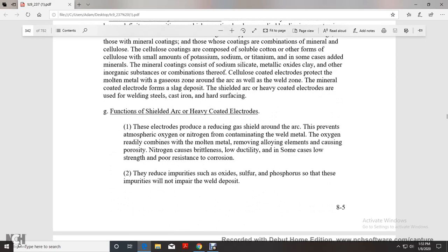Function of shielded arc and heavy-coated electrodes. One: the electrodes produce a reducing gas shield around the arc to prevent atmospheric oxygen or nitrogen from contaminating the weld. Oxygen combines with the molten metal, removing the alloying elements and causing porosity. Nitrogen causes brittleness, low ductility, in some cases low strength, and poor resistance to corrosion.